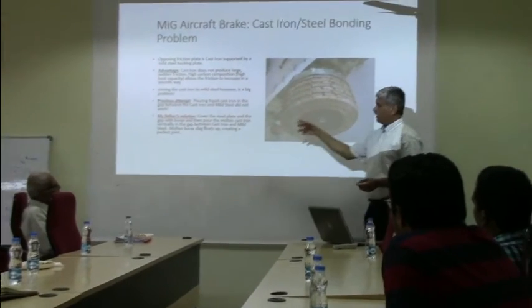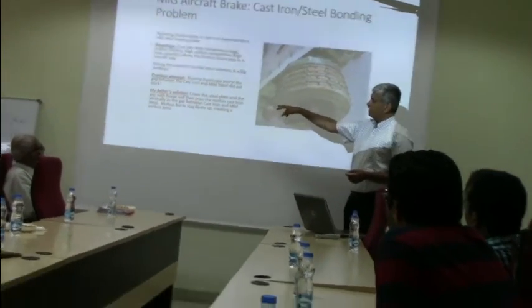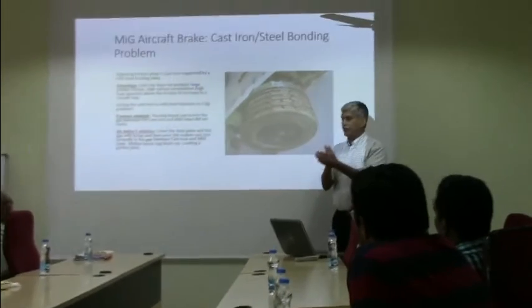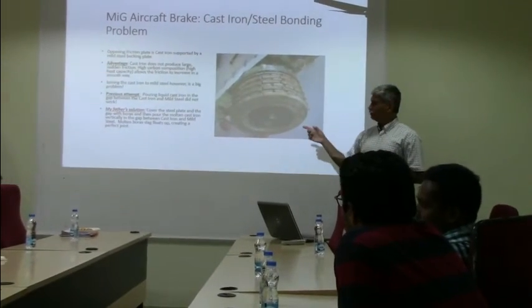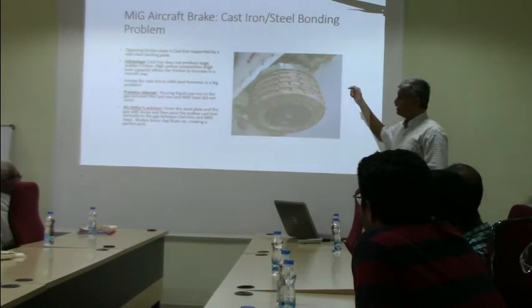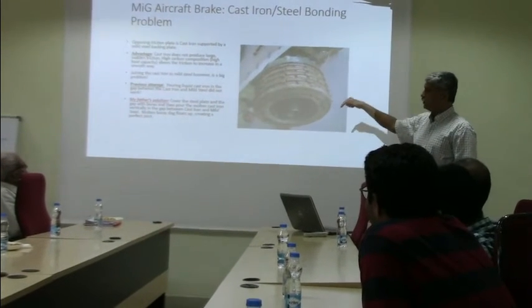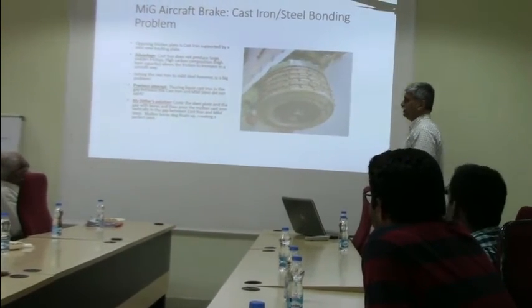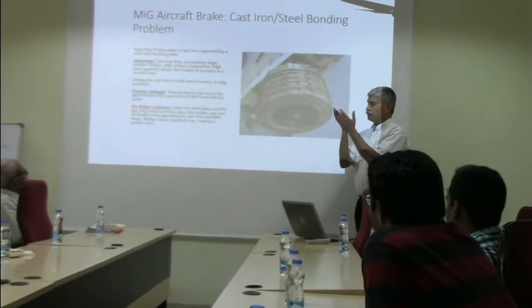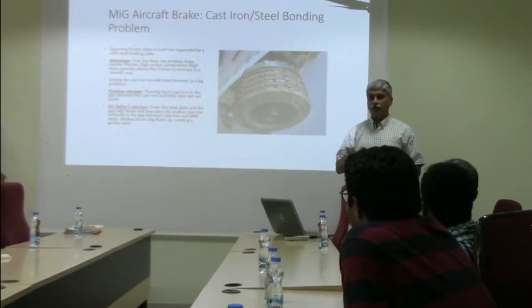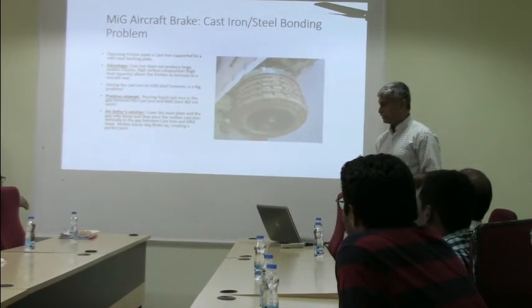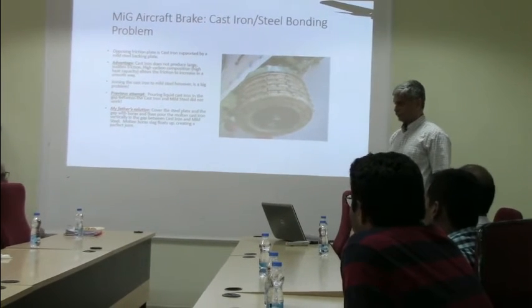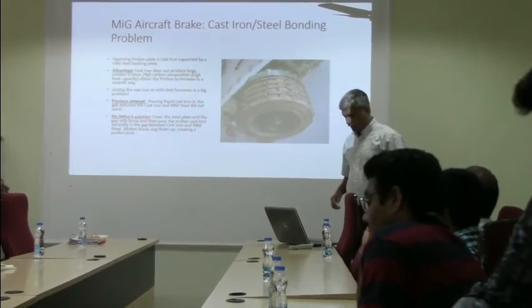So my father came up with the solution of covering the steel plate and the gap between the plates, about a centimeter or so, with borax, and then pouring the molten cast iron vertically in the gap between the cast iron and the mild steel. And so when the borax slag floats up, it just creates a perfect joint, right? It takes up almost all surface impurities. Right. So all the oxide and so on.